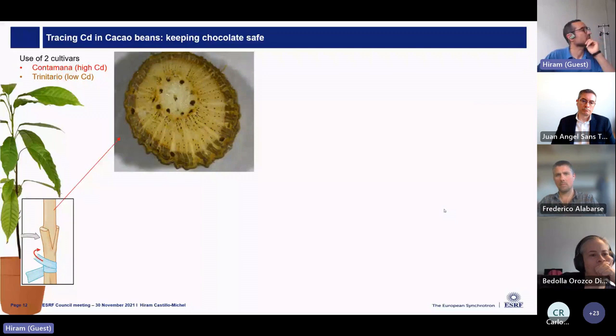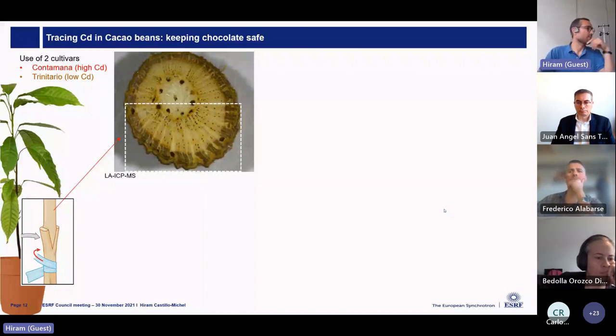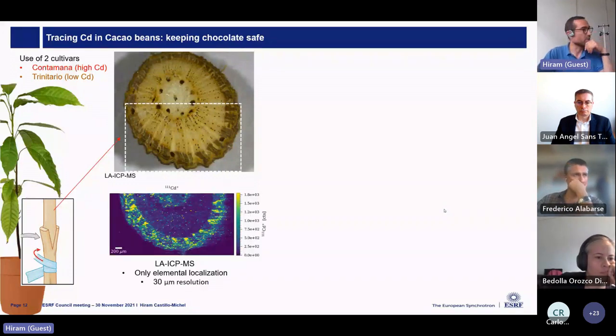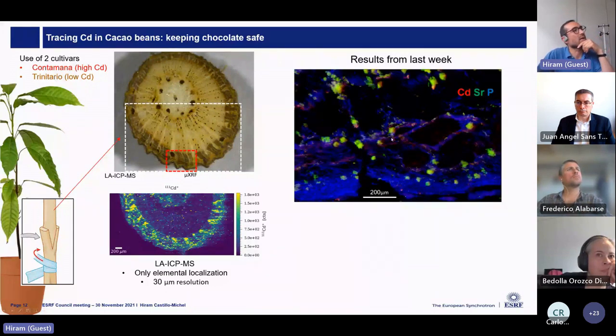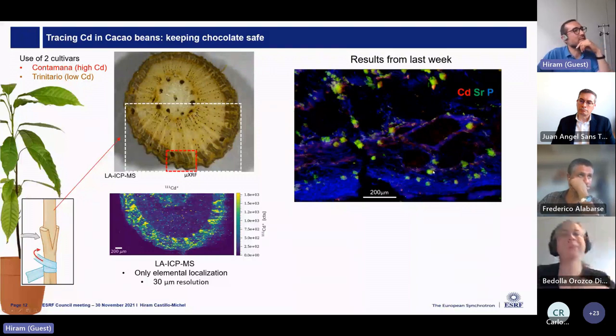So here I present an image of a branch. If we analyze this branch with laser ablation ICP-MS, you get a map of half of this branch, but the resolution is 30 micron. If you come to our beamline, for the time being you can do a smaller map, but the resolution is much better. And in that way, you can also detect low energy elements like strontium, which is colocalized with calcium. And you can see the shape of these crystals. These crystals are oxalate crystals that contain a significant amount of cadmium.